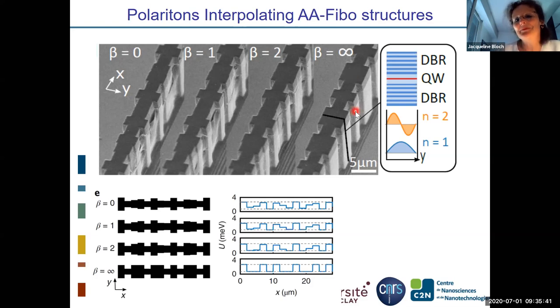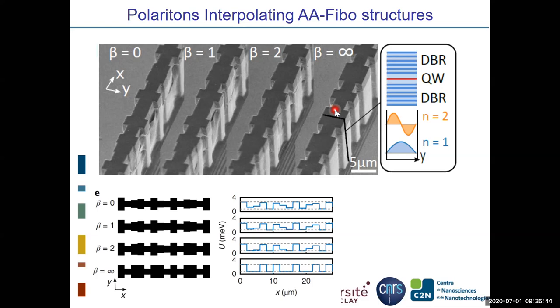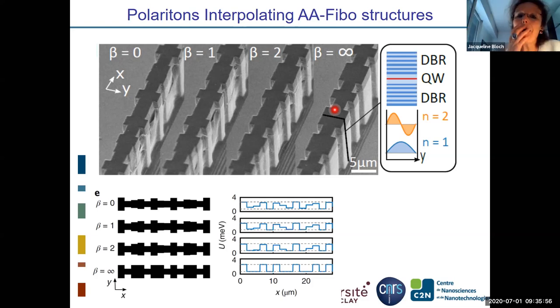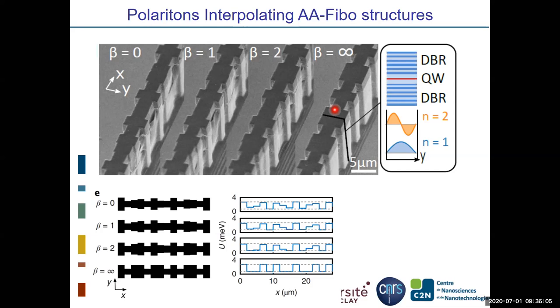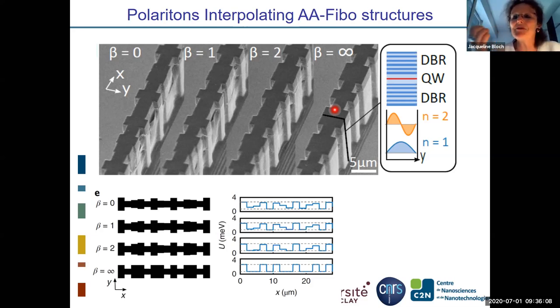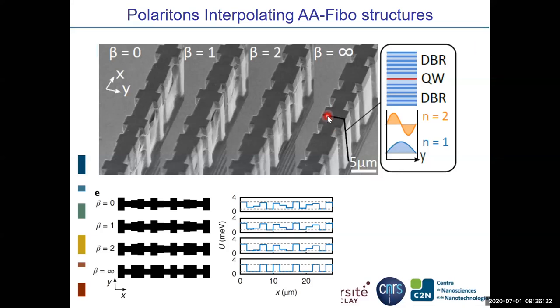I do have a question. In terms of the coherence length of the light, what is the maximum length scale that we should be considering across that axis? I think it can be of the order of 50 microns. It depends on the Q factor, but the Q factor is very big. It's of the order of 30,000 or 70,000. So the wave is very extended, and so they are able to feel that. Polaritons will never be confined within such a small trap. They will really average the potential.